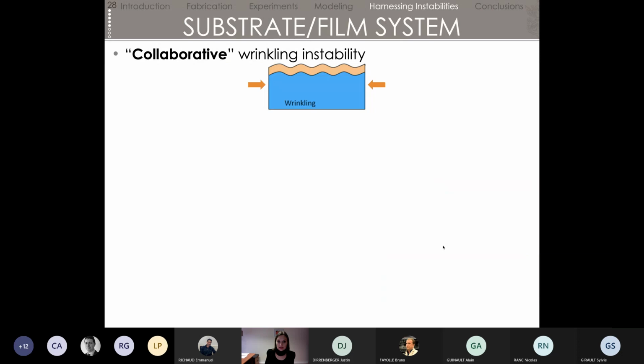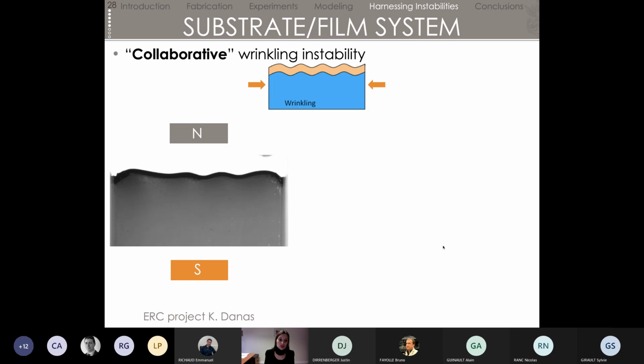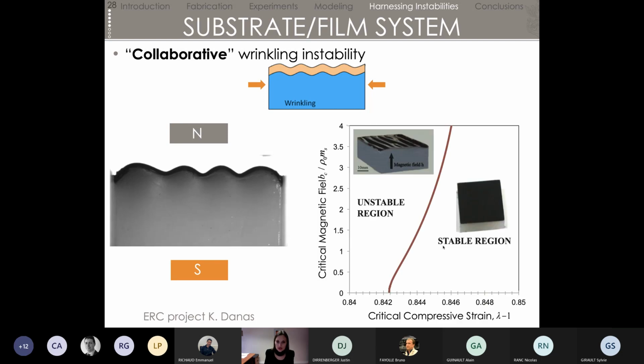So that's for this first device. The second device that we looked at is inspired from a very classical mechanical problem, which is the problem of stiff, thin films on a soft substrate. So you know that if you compress the substrate, you will end up with a wrinkling instability at the top of your film. Well, in fact, if you deposit a magnetorheological layer on top of a very soft substrate that is not magnetic, and you apply a really large magnetic field, you will have also this wrinkling instability showing up. And so the idea that Kostas proposed for ERC was the following: because we have two instabilities that are collaborative in some sense, we're going to play with both of them so that we reduce either the amount of mechanical compression we need or the amount of magnetic field we need to trigger those instabilities.